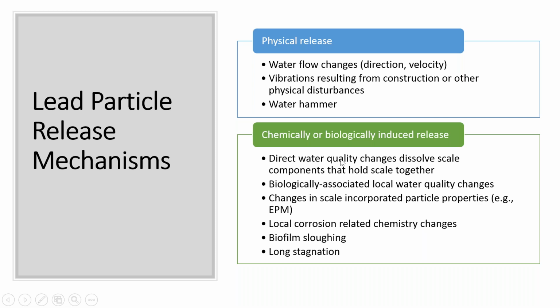Whereas there are also chemical or biologically induced release mechanisms, and this might be just direct water quality changes that dissolve scale components. And again, it's not just lead components; it could be any scales, or other things too. For example, there could be aluminum, or calcium that's incorporated into existing scales of, let's say, lead carbonates, lead phosphates, whatever it may be. If you disturb those, you might disturb the lead that's around them. Think of it as kind of the glue holding things together, and if you start to dissolve these things, you could have